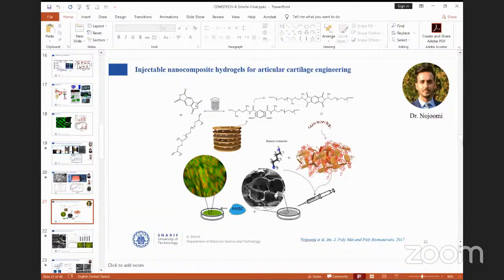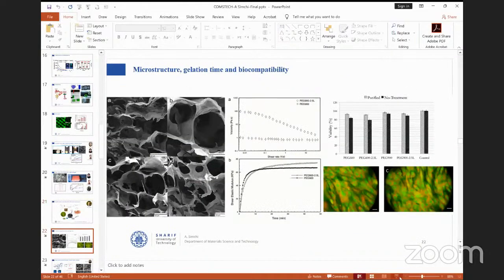He was successful to prepare such polymeric materials, and I will show you some results about that. The SEM picture in the left-hand side shows the structure of the hydrogel he made. The middle picture shows the gelation time, and the viscosity versus the shear rate shows it is injectable and it can be a gel after 10 minutes. And cell studies show that the stem cells remain active and can be proliferated and can be transformed to the target tissue. However, the problem of this study was the mechanical properties. The mechanical properties were not good enough.